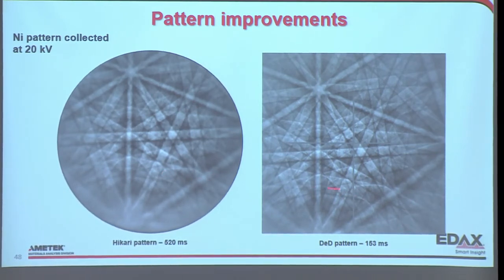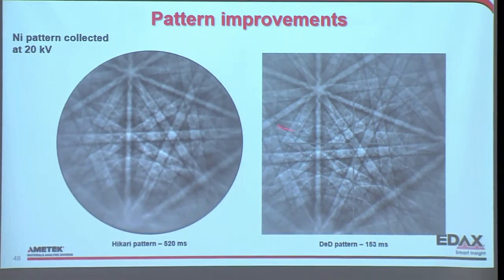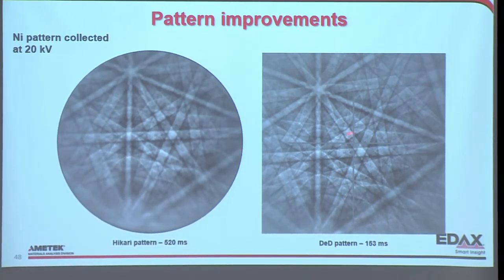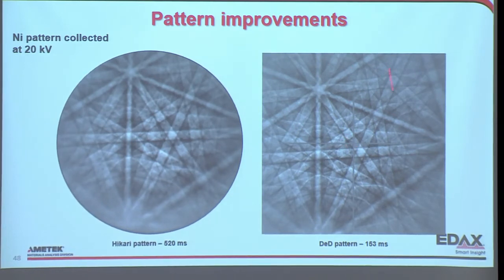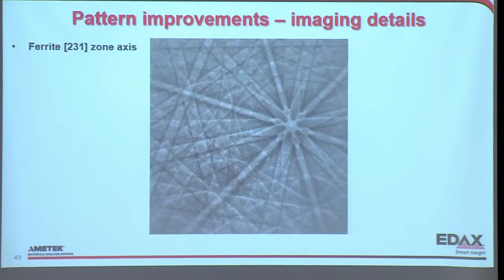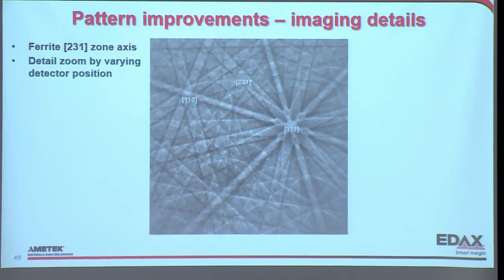You can kind of see it in here, but they're much more spread out. You see a lot of detail in the poles. What you see here is the seams. Like I said, there's four 256 by 256 chips. There's one here, one here, one here, one here. And so you can see some seams that we're still working on trying to reduce. This is a ferrite, and just the amount of detail here, you can see multiple orders of magnitude that there's no way you can see with a regular detector. And we can index them.